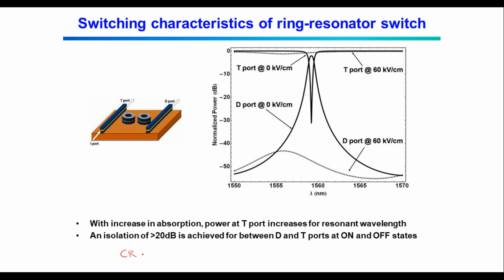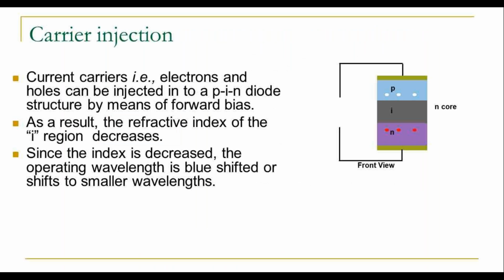Accordingly you can decide what should be the contrast ratio between the on and off states. Usually you would always prefer to have a contrast ratio greater than 20 dB. That means if you have 100 photons at the transmission port, you will have only one photon at the drop port. So you have a ratio of something like 1:100, a rough estimate. So with quantum mechanics, you can calculate all these things.